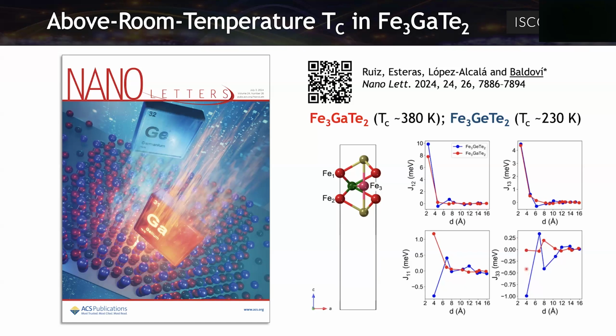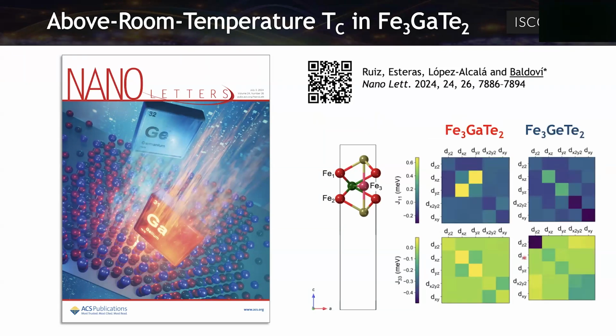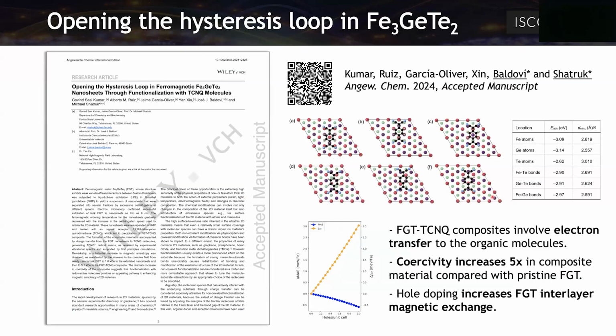So are these interactions responsible for this enhancement of the temperature, according to our calculations? And we can also explore which are the mechanisms. This is just coming from the interactions that are ferromagnetic or antiferromagnetic. And the last thing, this has been published just this week, well, accepted this week. In this case, we have tested the effect of TCNQ on iron germanium telluride. This is a nice collaboration with Mike Shatruk that is there in the conference, so he will be able to give more details about all the experimental part.